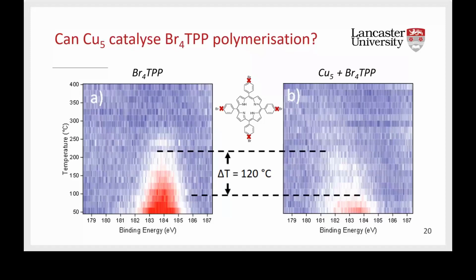So then we have a color scale. Blue means that there is no peak in the spectrum, while red means that there is a peak. So as you can see, the peak disappears around 225 degrees Celsius, meaning that the bromine has left the surface, so the carbon-bromine bond must have been broken.